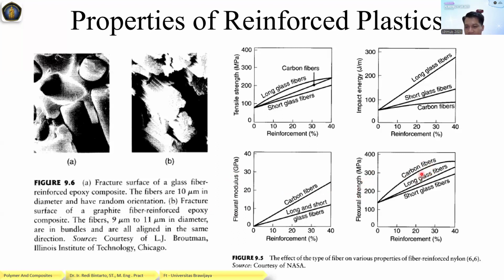And for flexural strength, next is long glass and short glass. Because of the long fiber, it has a function to strengthen the material. If short, because the fiber is short, the flexural strength is not as high as with long fibers. So this is the difference between long and short fibers. But for tensile strength, yes, long glass fiber is the highest. So we just compare glass fiber and carbon fiber.